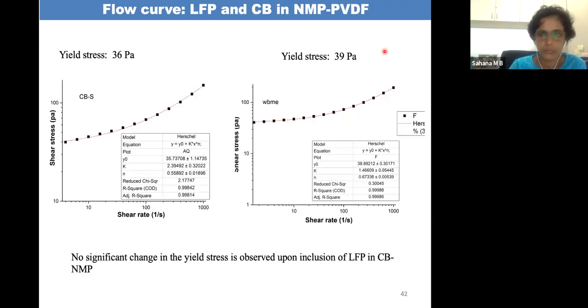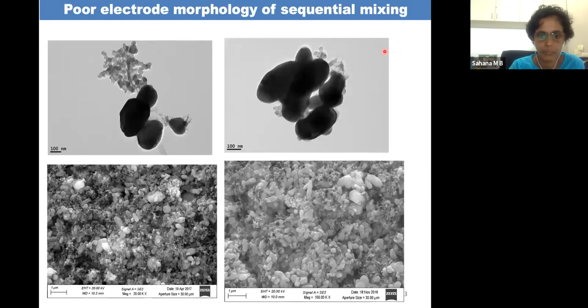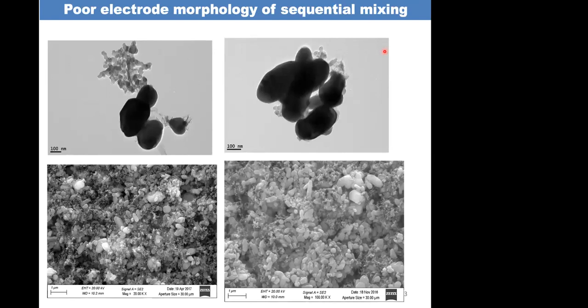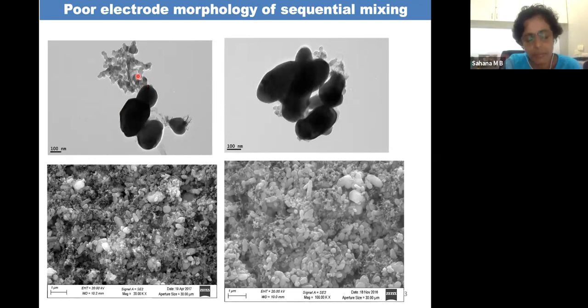I'll go a little faster because we have only 30 minutes, right? So what we do is, when we prepare a slurry, first we add carbon black to the PVDF NMP mixture, and then we add LiFePO4. The microstructure becomes extremely poor. What happens is, in some places the carbon black is separately agglomerated and LiFePO4 is separately agglomerated. This kind of structure is not good for the electrochemical performance of a cell.